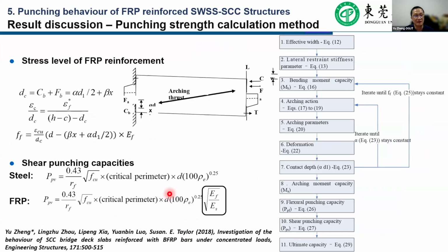In our study, the focus is that due to the increased height of the compression zone inside the concrete, the effective stress level of the FRP reinforcement inside the bridge decks needs to be predicted accurately. Therefore, we propose an integration method to predict the effective stress level inside the concrete bridge decks. We can use that to predict it. Furthermore, we propose a modification to predict the shear punching capacity, considering the difference between FRP reinforcement and steel reinforcement. Those methods have also been published in our paper in Engineering Structures.